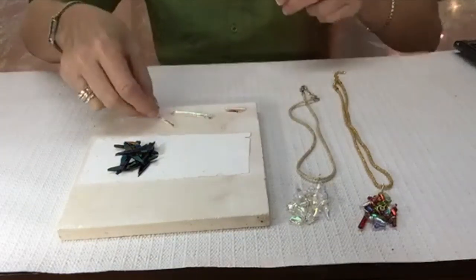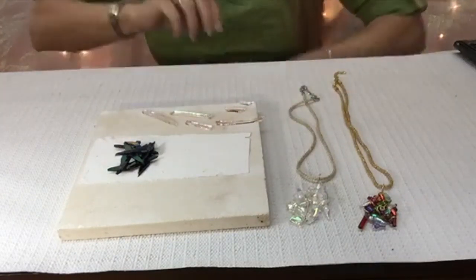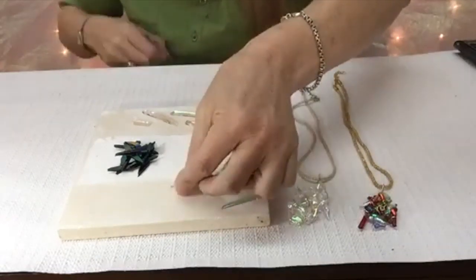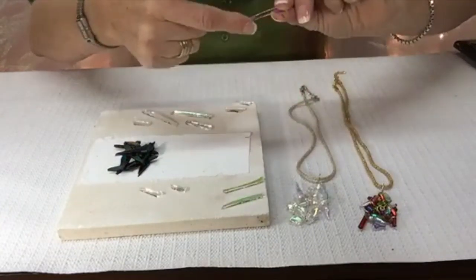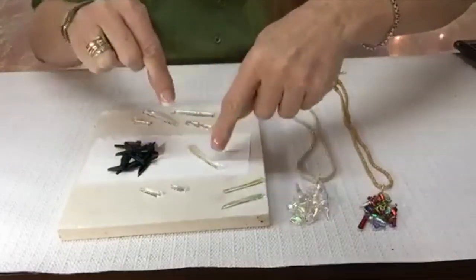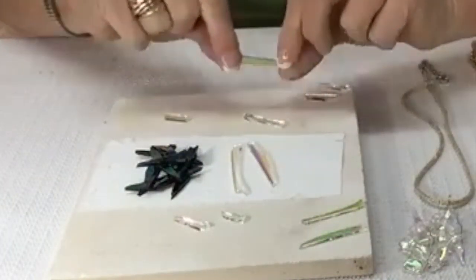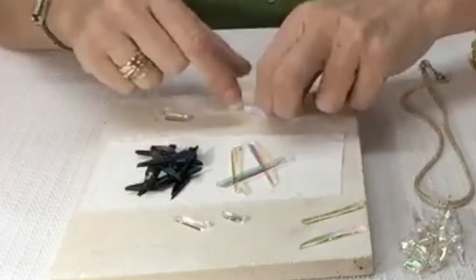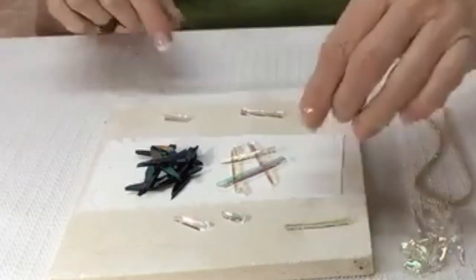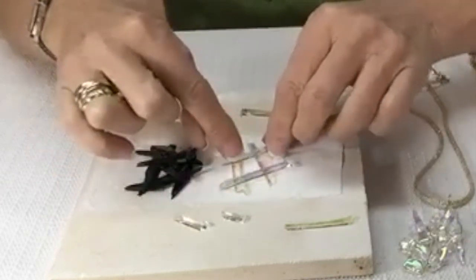There is an issue with the clear pieces you're going to have to be aware of. The dichroic coating is on one side, usually almost all the time. And what you have to be aware of is dichro doesn't stick to dichro. So I'm making sure that all my dichro is face down right now — my dichroic coating is on the bottom of this piece. I want to make sure they're all on the bottom, because if I put dichro up, dichro down on the next one, it won't stick to this layer. So it's so important that you keep these all going the same way, or they won't stick to each other and your piece will fall apart when you take it out of the kiln.